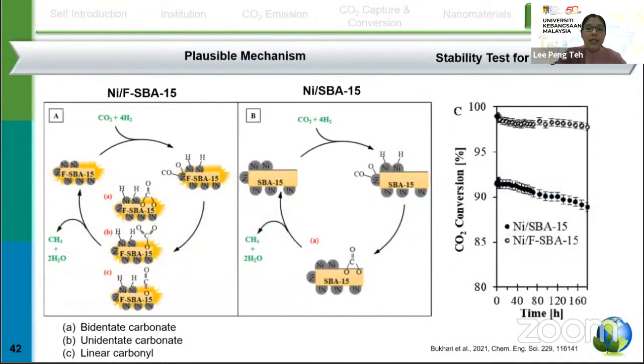We also synthesized the fibrous SBA15. With this fibrous SBA15, we studied CO2 methanation. In these slides, we propose the possible mechanism for this nickel fibrous SBA15 as compared to the nickel SBA15.